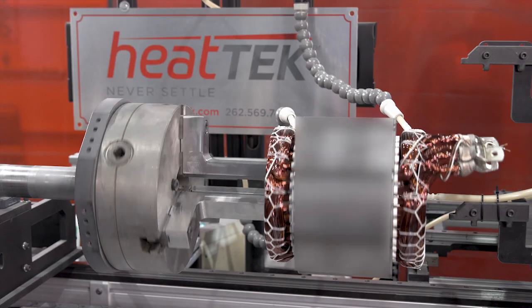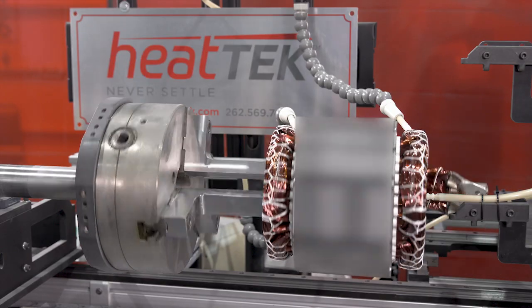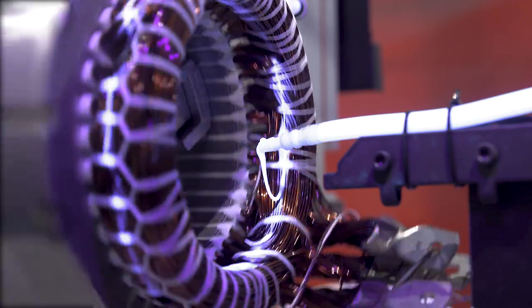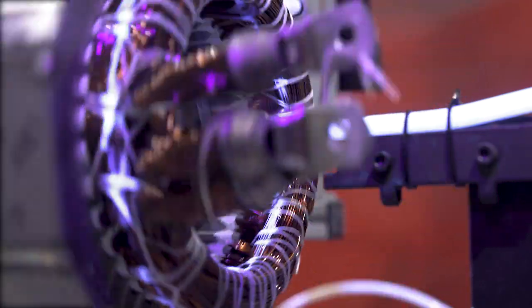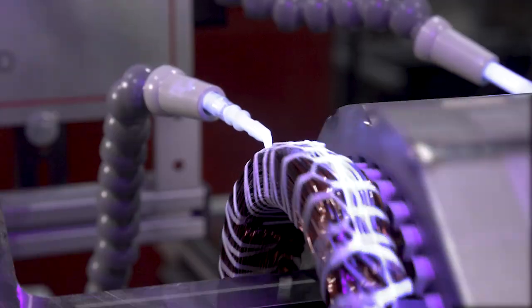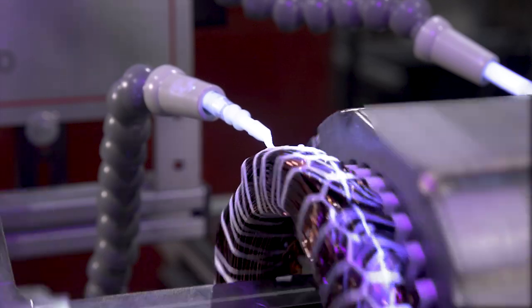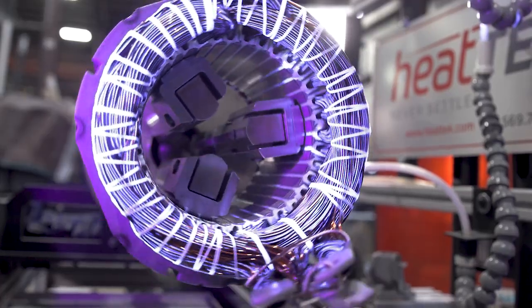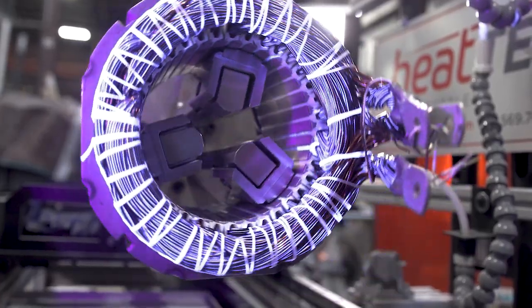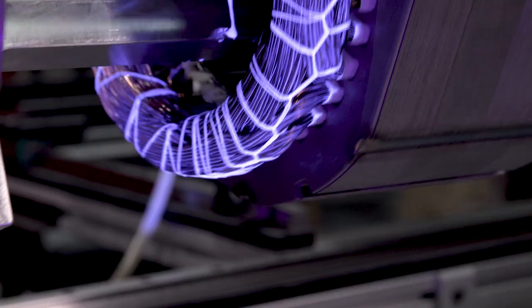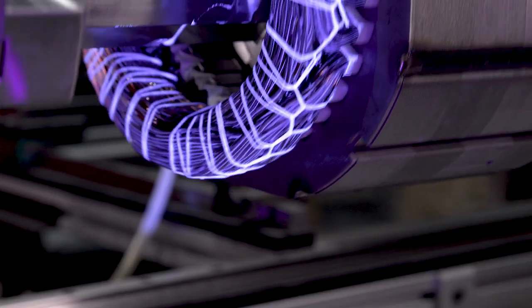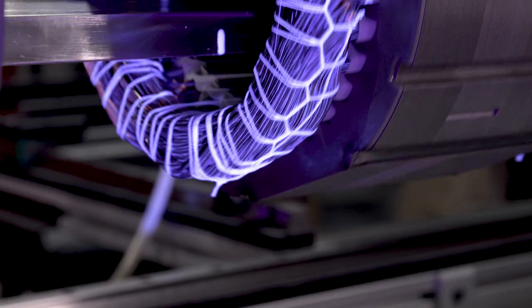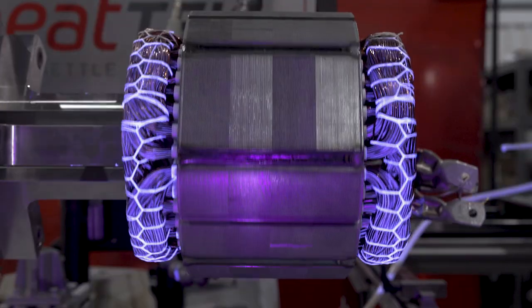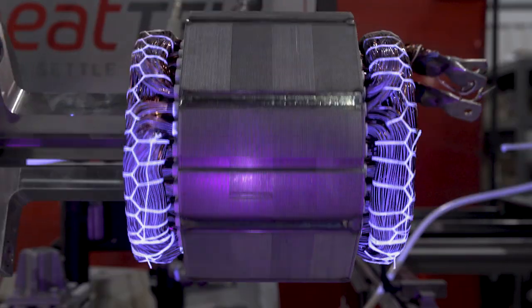In this video, you can see the EPIC ProPreg E240 being applied to a conventional round wire stator using polyester-polyamide-imide primary insulation, wire enamel. See how well the E240 absorbs into the end turns, and you can see on the finished product how well coated the end turns are, and there is no resin migrating onto the end laminations or on the ID or OD area of the stator.